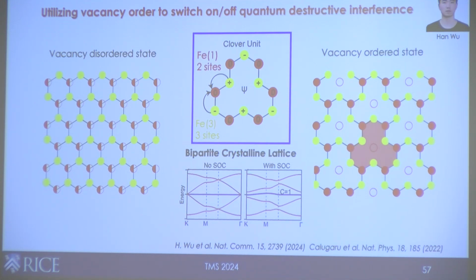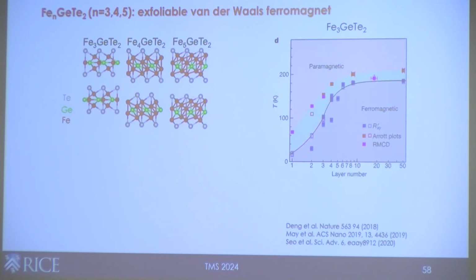So there are ways to create this, and why am I telling you this is because we found this accidentally in a material which is actually maybe not so strange. So that's known. So the material is iron germanium tellurium, and if you work in the 2D magnetic materials, you know that a couple years ago, this is one of the class of 2D metallic van der Waals ferromagnet materials discovered. It belongs to a large family of this, where you have van der Waals stacks of van der Waals slabs,